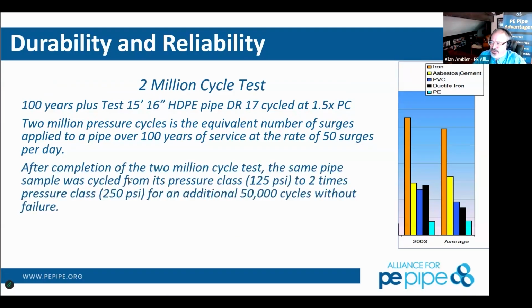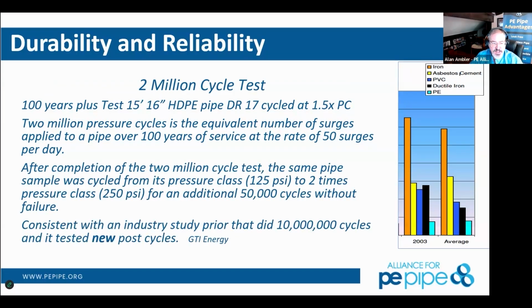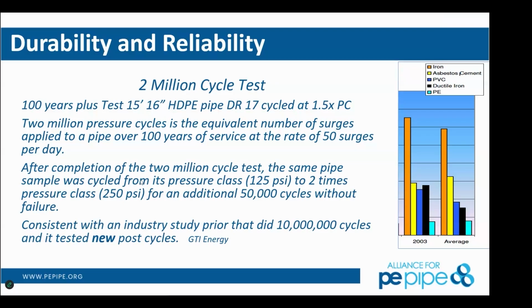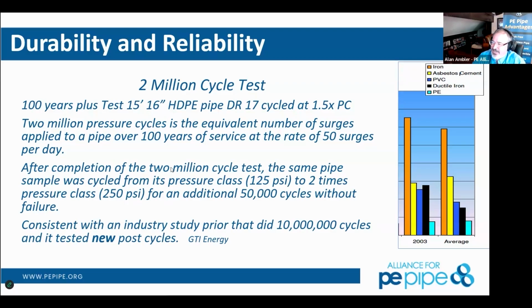That durability and reliability shows us through this 2 million cycle test. So this pipe material, in order to be listed on PPI's technical notes and reports 3 and 4, has to go through a heck of a lot of testing even before it leaves the resin manufacturing facility, and then also even more testing at Pipeline Plastics' facility itself. Mike, don't hate me, I'm talking a lot at this point in time. So there you have it. This 2 million cycle test really shows us that we're going through quite a bit of testing for that facility itself prior to even arriving on your job site as well.